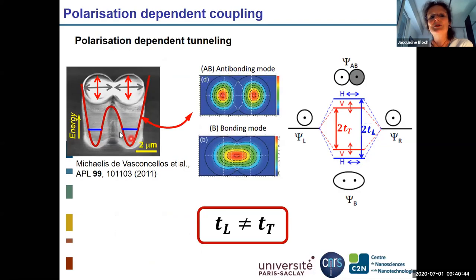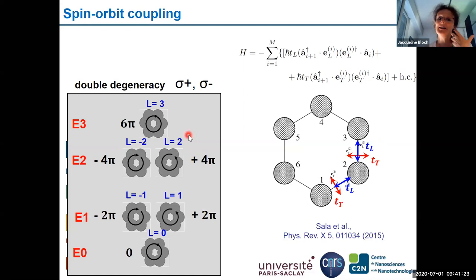Actually, to make a complete description of this molecule, you also need to take into account the polarization of light. If you compute Maxwell's equations and you look at the modes in such a structure, you find that the modes which have a polarization parallel to the bond do not couple to each other with exactly the same strength as the modes which have a polarization orthogonal to the bond. So it means that the splitting between bonding and anti-bonding modes will not be exactly the same for H and V polarization. So if we want to compute all the modes in such a molecule, we don't have six modes, but we have 12 modes now that we take into account the polarization. And then we have to write a tight-binding Hamiltonian where we take into account the fact that the coupling on this bond, for example, is not exactly the same for the blue and for the red polarization.